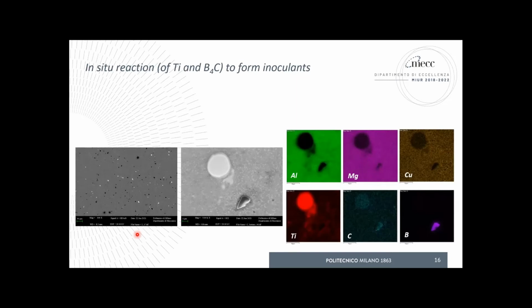Okay, here there are some micrographs just to show you what happens for real. Again, here's magnification of a titanium particle and a boron carbide particle, and here we have some EDS map confirming that titanium is being dissolved progressively in the matrix, but not all the particles are completely dissolved. Boron carbide is here. This is carbon. This is boron. Boron carbide is still there. But carbon, I don't know whether you can see it, is collecting around or at that particle, promoting the phases we were talking about.